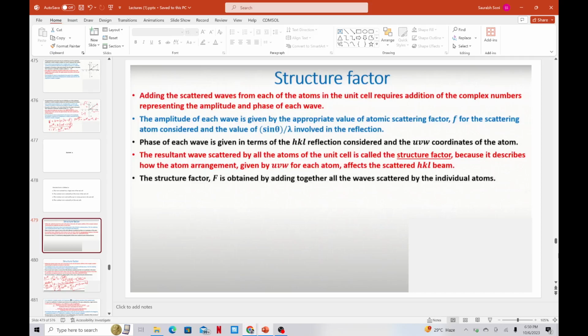Yes. So adding the scattered waves from each of the atoms in the unit cell requires addition of complex numbers, representing the amplitude and the phase of each wave. This amplitude of each wave is given by what? The appropriate value of this amplitude, which we discussed earlier, is given by the value of the atomic scattering factor. It is represented by f for the scattering atom considered and the value of sin theta by lambda involved in the reflection. Now, phase of each wave is given in terms of what? The hkl reflection which is considered and the uvw coordinates of the atoms. So this is about your planes and the axis coordinates. The resultant wave scattered by all the atoms of the unit cell is called what?